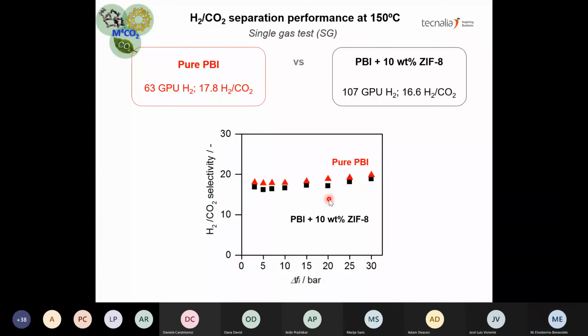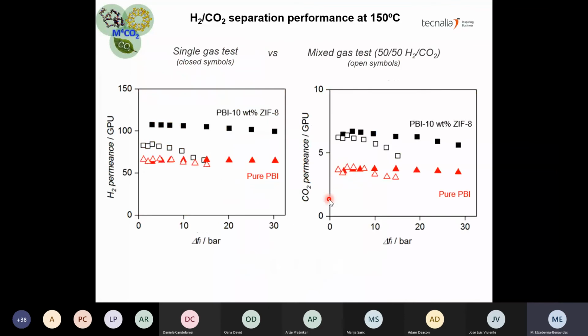So this was for single gases, but in order to be closer to real process conditions, we also tested the membrane for mixed gases. Mixed gas experiments are represented by open symbols in the graphs. As you can see in this slide, for pure PBI, the same performance was obtained for both single and mixed gases. However, for the mixed matrix membrane, a significant deviation from single gas experiments was observed for the mixed gas experiment. As you can see in the first graph, the hydrogen permeance was much lower for the mixed gas experiment.